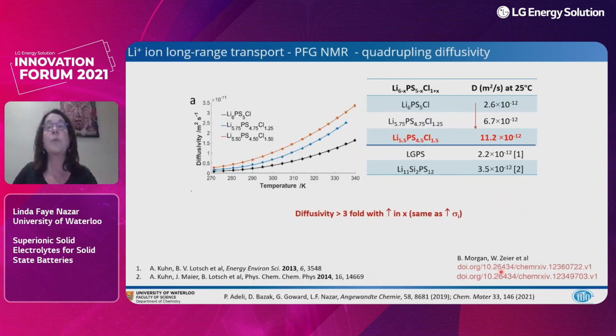And we carried out pulse field gradient NMR experiments. Well, actually, we didn't carry them out. Gillian Goward's group at McMaster University and her graduate student, David Bazak, carried them out. So David did these really elegant experiments where you push a gradient across a rotor, basically, or a material in a rotor in a solid state NMR probe. And that gradient literally pushes the lithium across the material. And so you can directly measure diffusivity in meters squared per second by this technique.